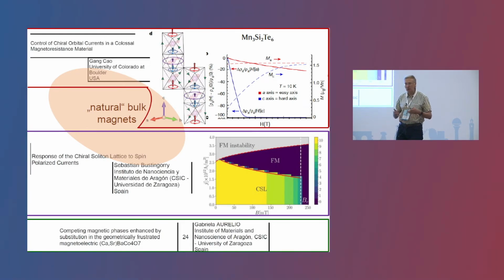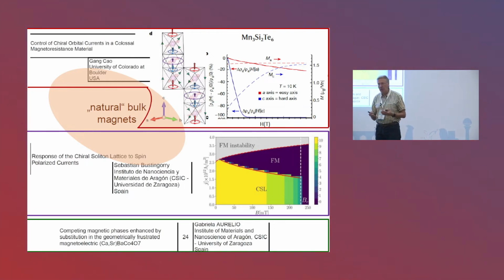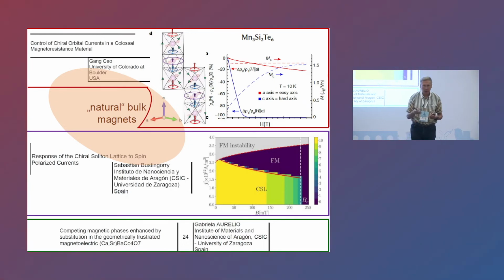So possibly due to the enhanced spin fluctuations or spin waves in this particular regime. Also there were some presentations, one of them given by Gabriela Aurelio about this very interesting magnetoelectric material, calcium, strontium, barium, cobalt oxide, where two order parameters, the magnetic order parameter, the ferromagnetic order parameter, and the electric order parameter were brought together, and that, of course, causes some interesting new phenomena which were discussed in this talk.